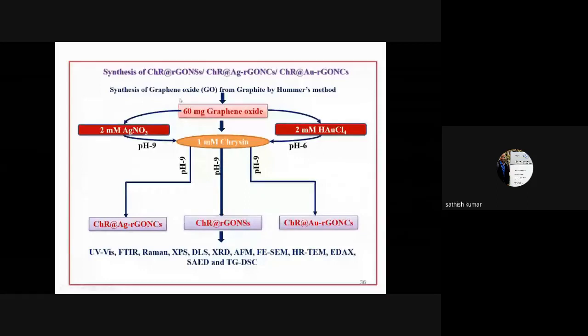So as I mentioned earlier, we cannot synthesize the reduced graphene oxide or its composites directly from the pristine graphite. So we have to go for an oxidation process called the modified Hummers' method. In this method, we use sulfuric acid and potassium permanganate as oxidizing agents to convert pristine graphite into graphene oxide form. From the graphene oxide, all the nanomaterials and nanocomposites will be synthesized using chrysin. As I mentioned earlier, we have to fix all the reaction conditions like pH, temperature, the reaction time, the quantity of the graphene oxide, the reducing agent chrysin, and the stoichiometric proportion. All these parameters have to be optimized. Then only can we get precise nanomaterials and nanocomposites.